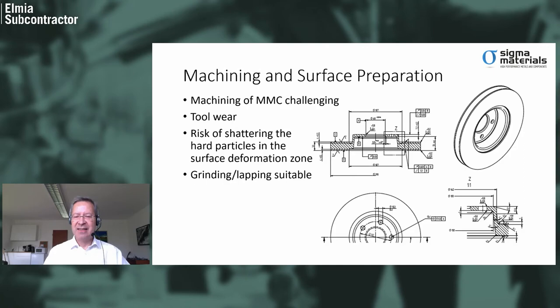Next slide, please. Is a bit tricky because MMCs are itself abrasive. They serve as a grinding wheel by themselves, which means that we have to use special tools to prevent excessive tool wear, and we have a risk of shattering the hard particles when we have a blunt tool and create a deformation zone. And as far as I can see, this is also one of the reasons why it is so difficult to create the formation of the transfer film, because if you pull out shattered particles from the matrix in the first break-in operations, it will never heal. So what we try to do is to apply grinding or lapping, which is more capable of preventing surface deformation and surface degradation. Continue, please.